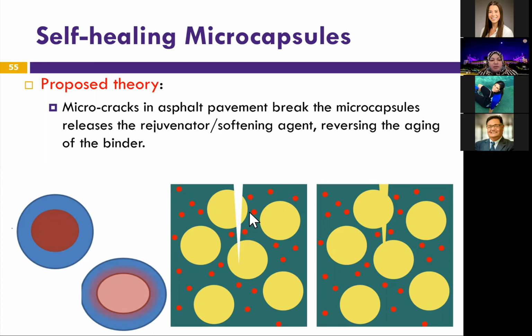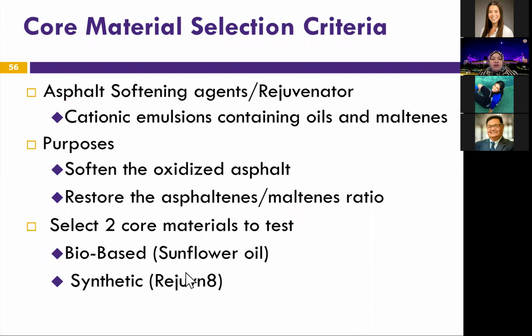So we start with the microcapsules. As you can see here, there is a urea formaldehyde shell that has the rejuvenator inside. It's mixed within the asphalt mixture. And when the asphalt starts to crack, it breaks the shell, releasing the rejuvenator, and it only releases a little bit at a time, so it does not soften the binder. We experimented with two different core materials or rejuvenators, a bio-based oil, sunflower oil, actually the one we use for cooking. It worked very well. And a synthetic one, which is known as Rejuvn8.